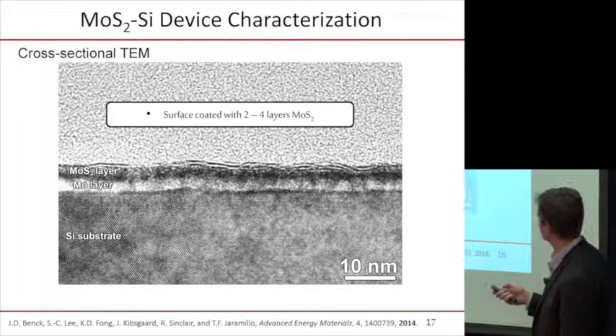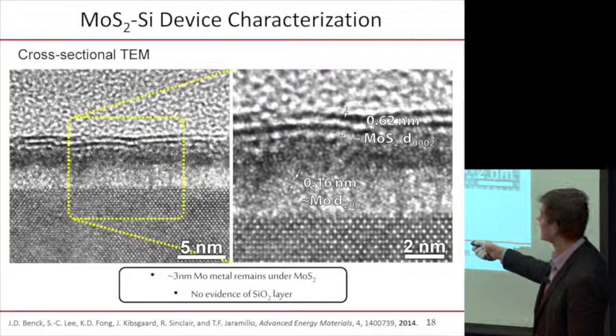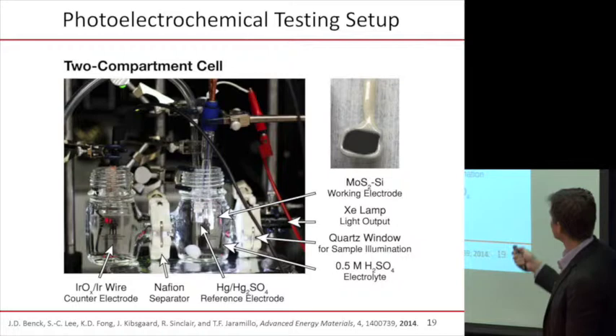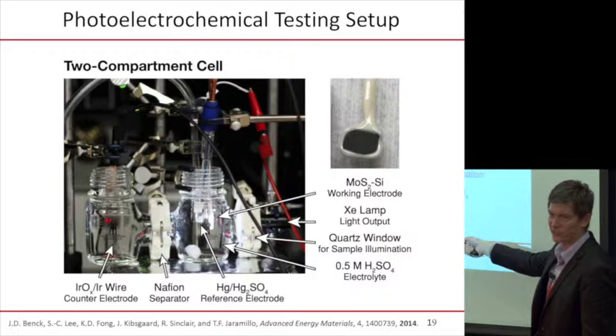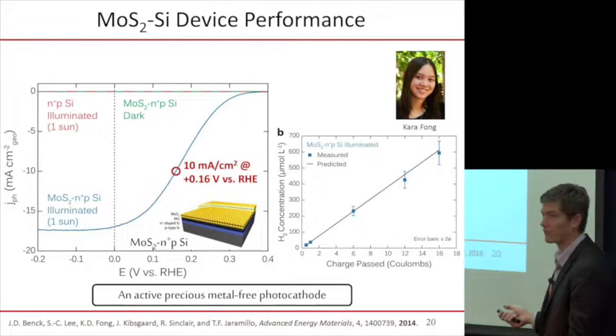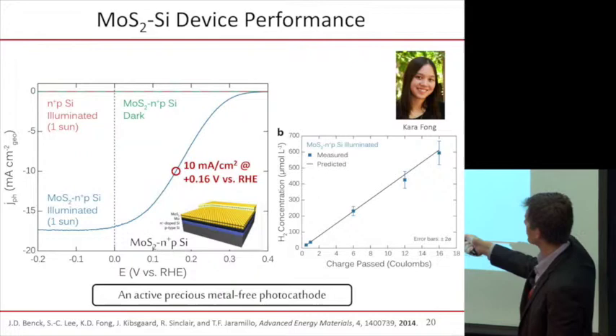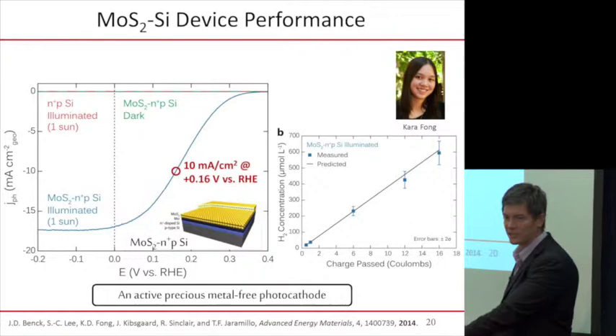And what you see here is this really thin layer of MoS2, looks kind of like graphite, sitting on top of ultimately a silicon wafer, PN junction solar cell. We take this material, we encapsulate it in epoxy, and we dunk it under water, not just water, sulfuric acid, 0.5 molar, shine light onto it, and we saw what happened. The thing evolved hydrogen beautifully. Here's another current versus voltage curve. All the curves I was showing you before were on the left because thermodynamically you need to be on the left side of zero to make hydrogen from water if you put in electricity.